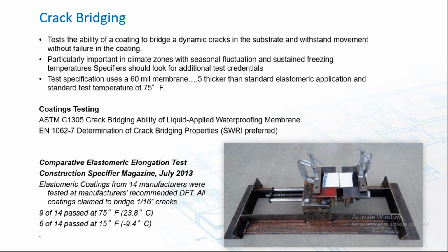And again, the test procedure can be modified to suit an individual's ends, but I think it's important here to reference the Construction Specifier magazine article back in July 2013, where they actually assessed the performance claims of 14 manufacturers with their elastomeric coatings that said they all passed at recommended dry film thicknesses. They ran a subsequent test and found that really only 9 of the 14 passed at 75 degrees, and even fewer passed at freezing temperatures. So there are test biases, no doubt, but there is also test execution bias as well.